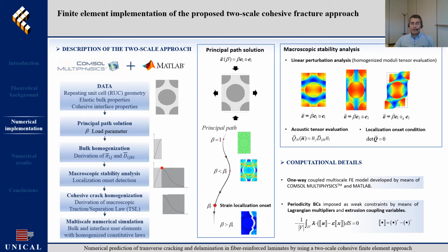Well, the overall stress-strain response up to localization and the homogenized traction separation law have been computed by using a finite element procedure able to follow the principal path of the analyzed unit cell, in combination with subsequent coupled macroscopic stability analysis for the detection of the macrostrain localization, which involved the solution of 3 independent linear perturbation problems at each loading step. Finally, a post-processing step is performed to extract the homogenized traction separation law from the micromechanically derived stress-strain relation. In order to automate all these sequential computational tasks, an ad hoc MATLAB code has been used within the commercial environment COMSOL Multiphysics.